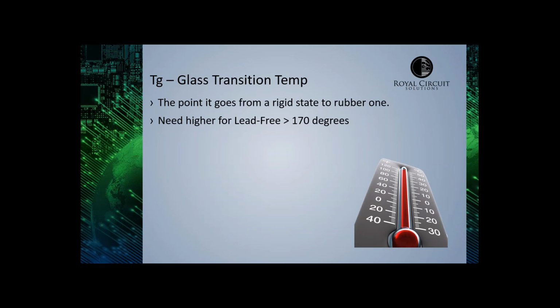Going through this, when I was in aerospace, this seemed to always be a constant source. Like, okay, how many reworks can we do? As we take and replace components constantly. Over the years, I think there's been a lot of papers done, but there's been nothing to say, okay, a glass transition temp means this number of reworks can be done. With lead-free, you want 170 degrees or higher. And the glass transition temperature has kind of become the standard for reliability, as that is the point when the thermal rate of expansion goes to the highest level. And the one we talk about most and is called out for lead-free applications.